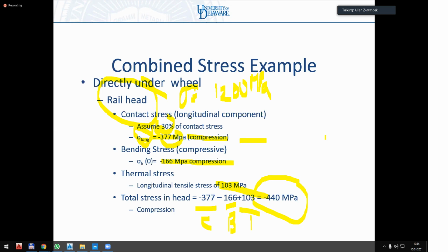So in general, waving my hands and knowing it varies greatly depending on the vehicle I'm using and the speed I'm traveling and the temperature change, etc., my largest component is the contact stress at the head of the rail, and that's going to be maybe between 30 and 40%, maybe a little bit higher than that. And then the bending stress is going to be between 20 and 30%, and the thermal stress is going to be of the order of maybe 20%, 25% as well. But I'm waving my hands a lot because it's going to vary depending on the wheel load, the speed, the track modulus, the neutral temperature, the actual air temperature or rail temperature. All of those are going to affect the relative ratios of those.